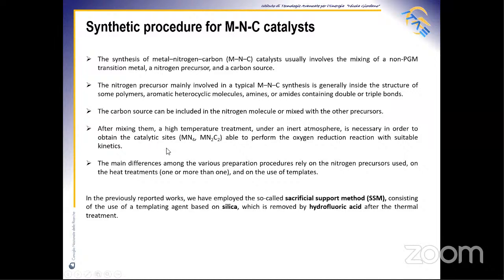And after mixing the precursor, a high temperature treatment is necessary in order to obtain the catalytic sites like metal N4, metal N2C2, that are able to perform the oxygen reduction reaction with the suitable kinetics. The main differences among the various preparations rely on the nitrogen precursors used, on the heat treatments, one or more than one, and the use of templates like silica.